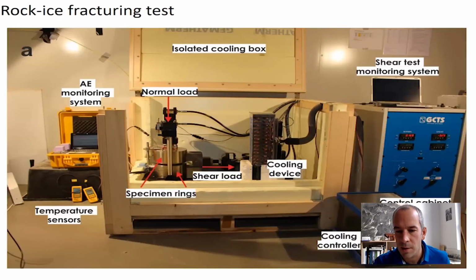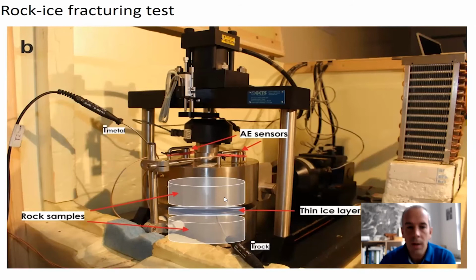And the last thing we explore in the lab quite a little bit is what happens at rock ice interfaces, because we know from bigger rock slope failures in the Alps that rock ice, if you have a bigger detachment at the Matterhorn, what you see after it is the ice that stays on the fracture behind that. So we have, in the last stage of the instability, this rock ice fracturing. This we test in this shear box, which is now in a cellar here in Munich, and we use sandwich samples, where this is not a slice of ham or something, this is a slice of ice in between, and this is a Zugspitze limestone, this is a Zugspitze limestone, so we make this test.